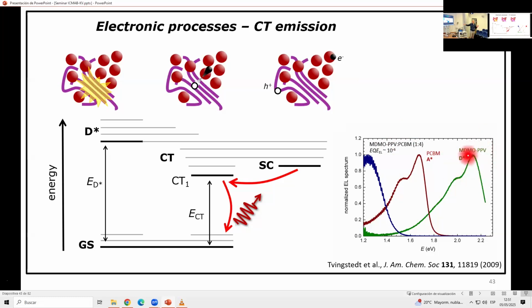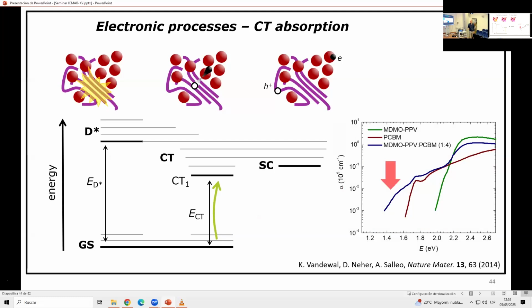This is about 1% efficient. PCBM is also not a very good emitter. But that interface emission has a quantum efficiency of 1 in a million, so a lot of non-radiative decay. The absorption is also there. We saw it before. Here you see it again for this particular blend. So you have some subgap absorption related to this transition.